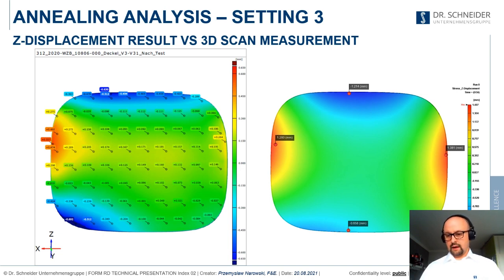And so at that moment, we can say that it makes no sense to just introduce more complexity in the modeling of the annealing process to make it more accurate, because it doesn't really improve our results much. The problem is in the injection molding simulation, and in that case, especially in the prediction of the in-cavity pressure, because by introducing the hot runner geometry, we introduced additional pressure loss in our system, and of course we changed the pressure in our cavity during the whole cycle. So we decided at that point that the best way to improve our displacement results would be to improve the prediction of the in-cavity pressure, of the pressure curve during our cycle.